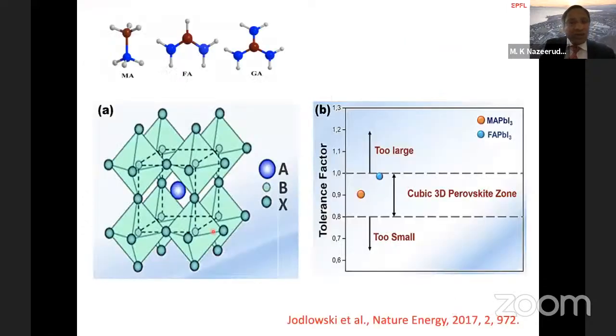So look at the methylammonium, formamidinium, and guanidinium. These are the three cations I have taken as examples. This is the Goldschmidt tolerance factor, where if the cation size is within this range, you form the cubic three-dimensional perovskite phase. If the cation size is too big, it will not form the perovskite, and if too small, it will not form the perovskite.